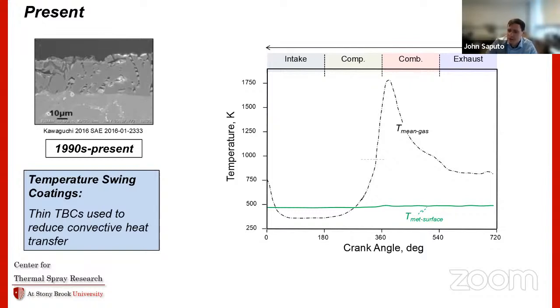So there's a couple of interesting things that happen here. There's a small portion of this during the intake cycle where that wall is hotter than the gas. So that tells you that the heat is going to transfer from the hot metal surface in the system to the cold intake gases. And during the compression and combustion strokes, there's going to be a huge temperature gradient going the other way. So heat transfer is going to go one way and then immediately turn around and go the other.